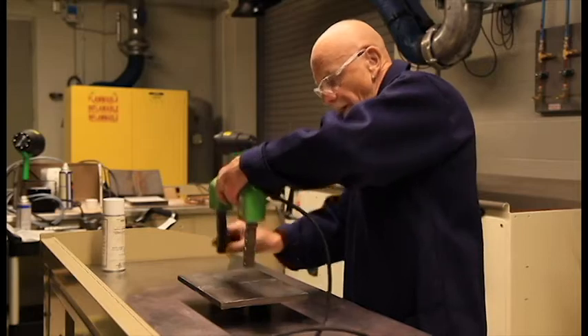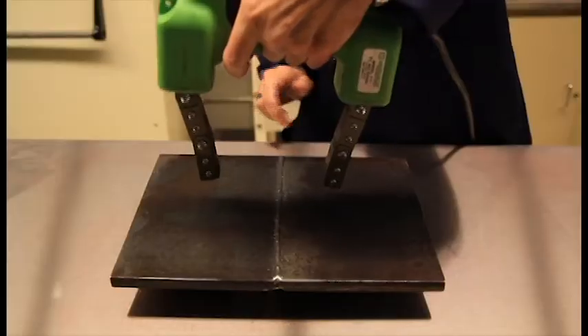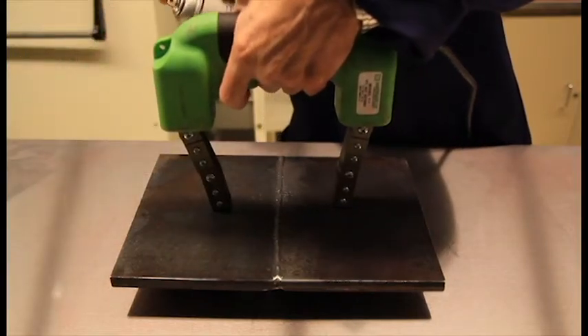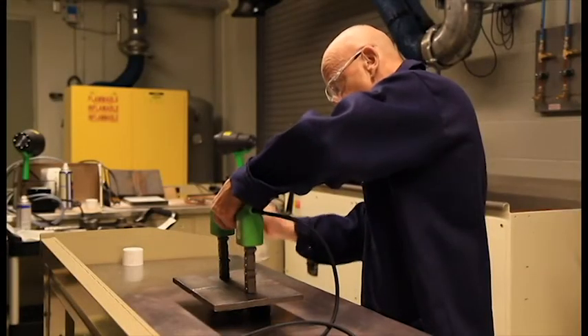The yoke is then applied across the weld, including an allowance for the heat affected zone, and is switched on. This induces a magnetic field that travels directly between the two poles of the yoke.